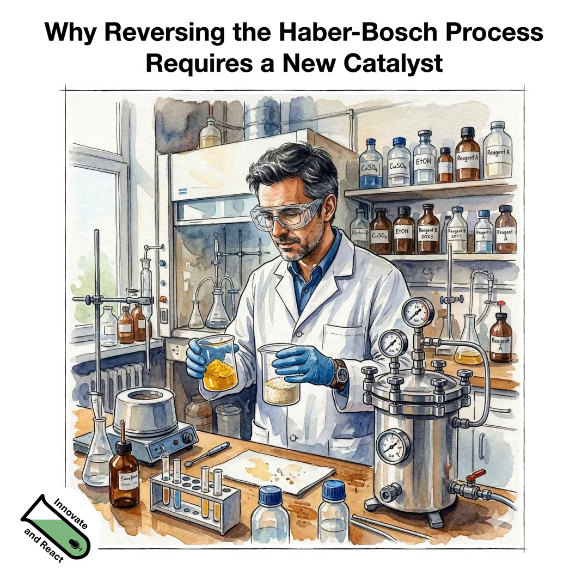Now we talked about iron and cobalt, but there are also other metals. And one metal which is also very good at this reaction is ruthenium, right? Yes. And there it is very prone to react with nitrogen. Yes. So it is not about forming the strongest bond to nitrogen, but in catalysis we have this famous Sabatier principle, which says that you need an intermediate interaction of the surface atoms to the intermediates, because if it's too strong, then the following steps will become rate determining, and if it's too weak, then the formation step of that intermediate would become rate determining.